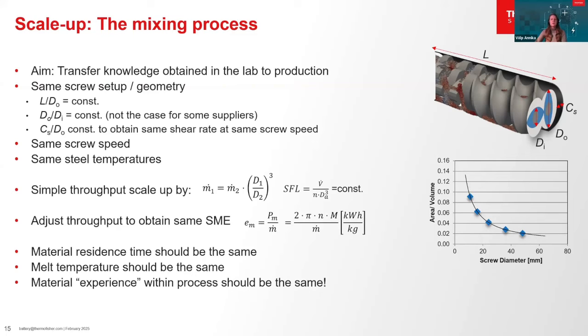Keeping the ratio between screw to barrel distance and screw outer diameter constant is essential. This helps in achieving the same shear rate at the same screw speed. Then we should use the same screw speed in both settings to maintain the same mixing intensity. Maintaining the same steel temperature is important to ensure thermal consistency throughout the process. But have in mind that the heating surface to volume ratio drops with increasing screw diameter, as shown here in the graph on the right.